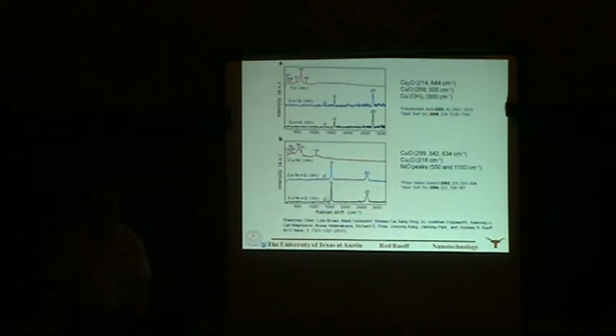And the same thing with Raman. Raman can delineate the presence of oxide formation in the unprotected or uncoated regions from graphene-protected regions where they have neat copper.